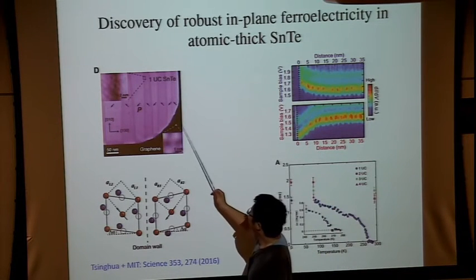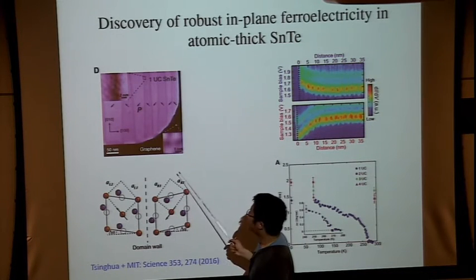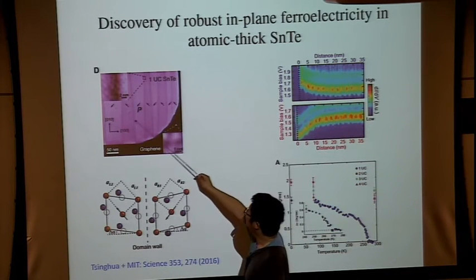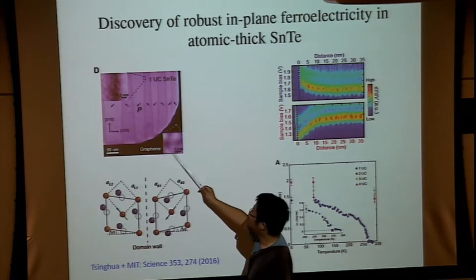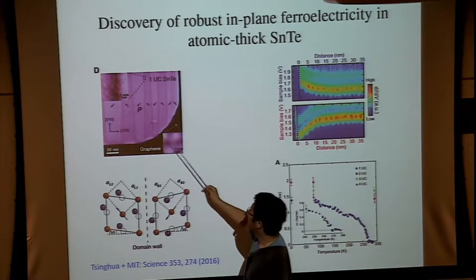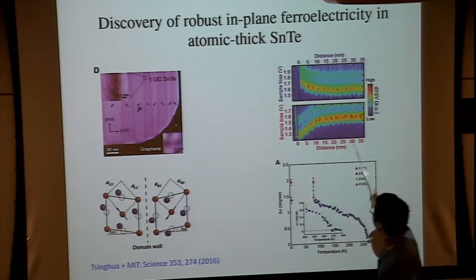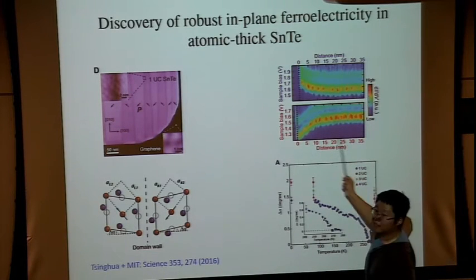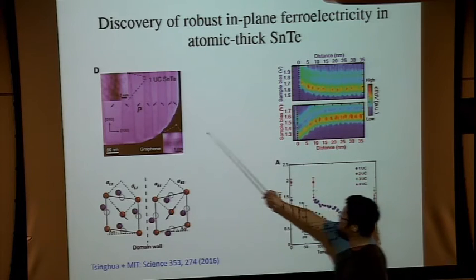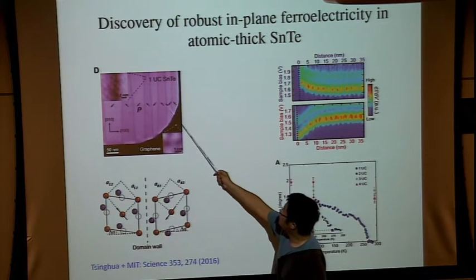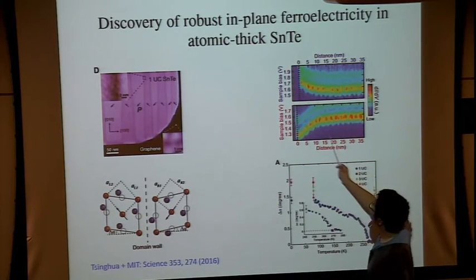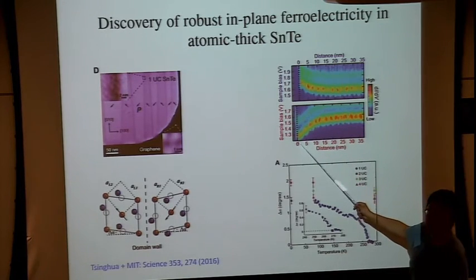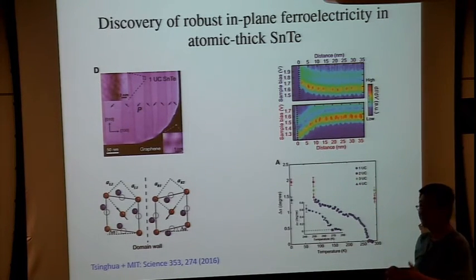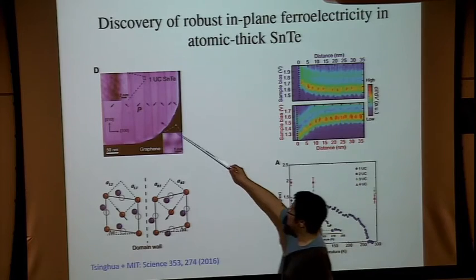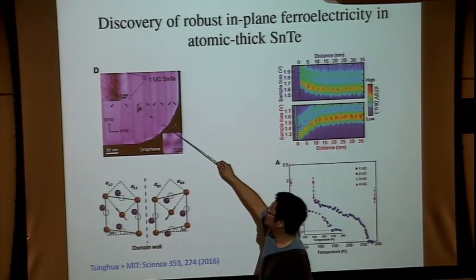But when the tin telluride is atomically thin, in the topography, you see that there are different stripes here. These stripes are different ferroelectric domains. You know that because if you look at the dI/dV spectrum as a function of position, whenever you come to each domain wall, you see that the bands either bend up or bend down. This is telling us that there's a build-up of charge. There's a net internal electric field that is caused by band bending.